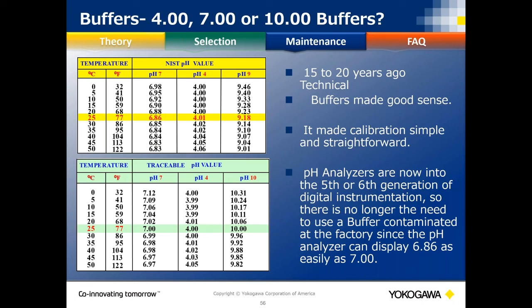You can spot check after you do the 2-point with the 9 or the 10, or you can do the 3-point. The 9 or 10, the reason why we don't want you to use those is because look at the huge difference from the 9.18, how much buffer they had to add to it to get it up to a 10 pH. If you use these, you want to use it right away and throw it out, because the minute you open that bottle to air, carbon dioxide seeps in and starts decreasing the pH value of your 10. So it's the least stable, just naturally, and affected by temperature, okay?